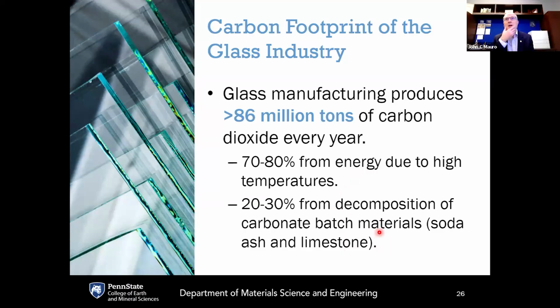Now, as happy as I am with all the cool stuff we did at Corning, the fact remains that over 90% of the volume of glass that is made is what's called soda-lime silicate glass. This is the ancient glass material that has not changed in a very long time. It's called soda lime because two of the primary ingredients are soda ash, which is sodium carbonate, and limestone, which is calcium carbonate. And when they melt, they decompose into oxides. They release carbon dioxide into the atmosphere.